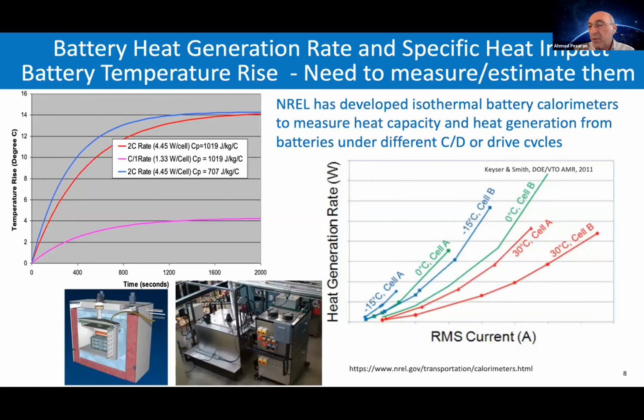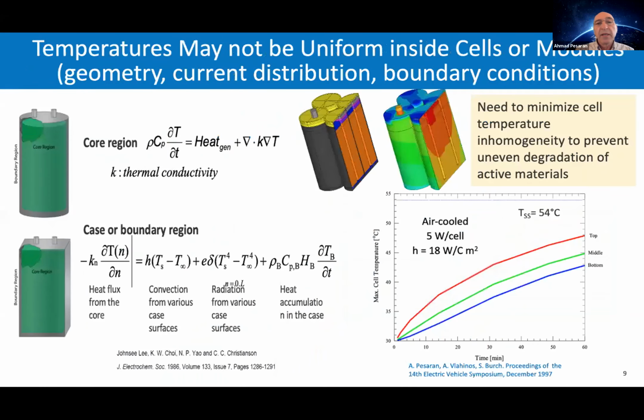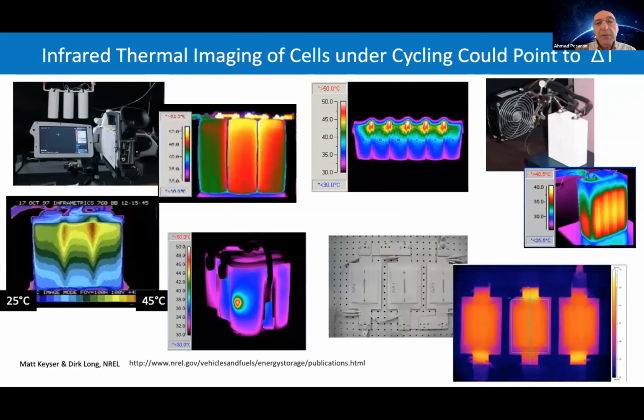This is an example of how the heat rate changes. At NREL, we have used this isothermal battery calorimeter to measure heat generation as a function of RMS current and drive cycles, and you can see each battery is different, and temperatures are different. We have heat transfer in modules, and you can see here, with air cooling, there is a temperature non-uniformity of about 5 to 8 degrees C within one cell. So we need to make sure we keep that down. Thermal imaging can show potential hotspots that we can see here.